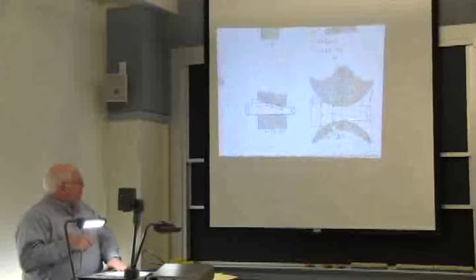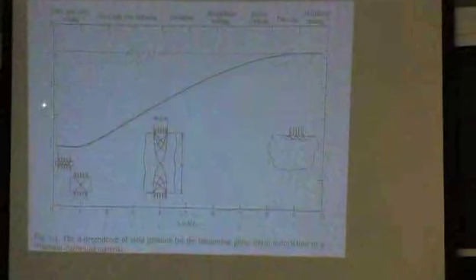So this is sheet metal rolling, and there's a delta value for that. Well, there are lots of different delta values, but now let me show you the most important plot in my part of this course. Figure 7.1 of Backofen is the yield stress plot. The pressure that you're deforming this thing with, the uniaxial compressive strength P, divided by 2 times the shear yield strength. Well, at a value of 1, you're just talking a simple compression test. That's how you measure the compression strength of the material. P is equal to 2 tau y, a Mohr circle type of thing.